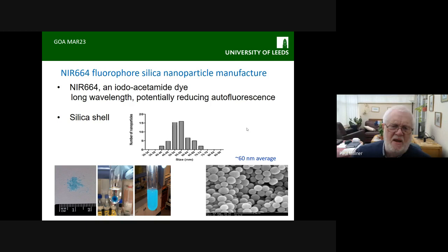So he was able to make silica particles, and he was able to put NIR664 in them, which is a long wavelength excitable dye. So it's excitable in the sort of red regions. And that's quite important if you're doing medical work, because tissue tends to absorb blue light. And you can see the size of those particles, and there's an electron microscopy image there. They're on average about 60 nanometers or so in diameter, so an ideal size.